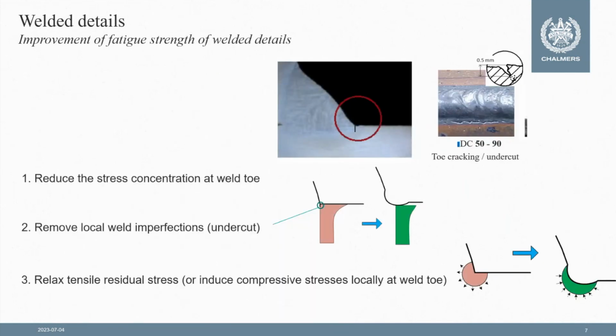Now, if we would like to enhance or improve the fatigue performance of welded details, particularly the category that we are looking at here, in which the fatigue crack starts from the weld toe, there are in principle three methods, or three actions that we can take. The first one refers to reducing the stress concentration at the location of crack initiation at the weld toe by having a smoother transition between the weld and the base metal.